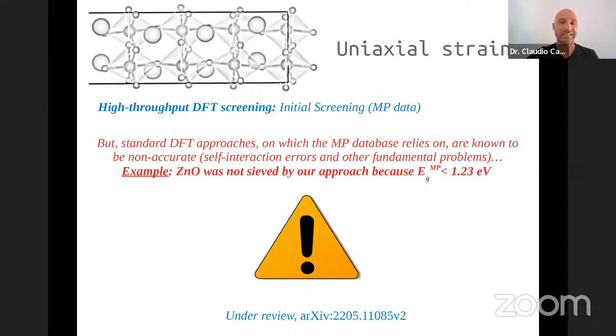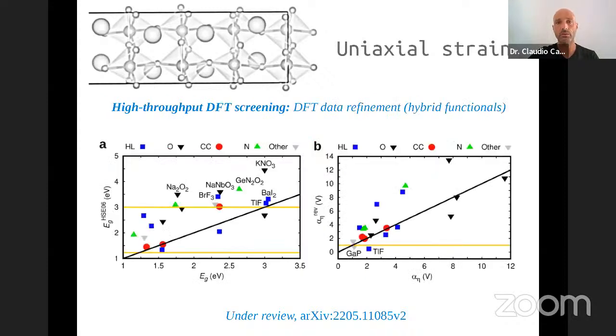That we know that particularly are not good for these energy band gap and band alignments properties that we are interested in, right? So for that reason, what we did was to refine the data found in the Materials Project. Of all those 40-something material compounds that we first sieved from the Materials Project database, we recalculated the energy band gap and the value of the alpha piezo photocatalytic parameter that we define, with much more stringent conditions, by using hybrid functionals, and by using quite large energy cutoffs and K-point grids.